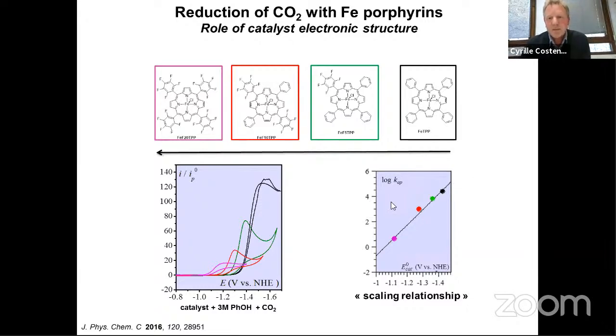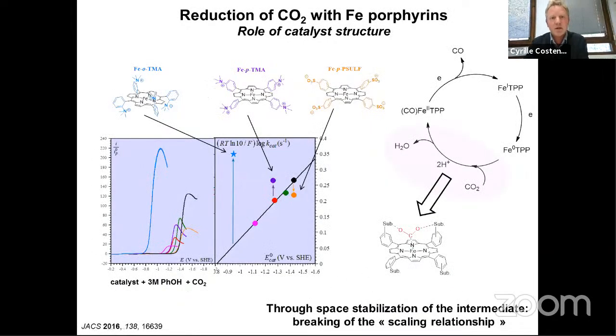Okay, so it seems that you are kind of stuck because what you would like is to get a high rate constant at positive potential, because as I said previously, the catalytic process is pinned at the standard potential of your molecular catalyst. Okay, so now the question is would it be possible to design a catalyst that will have a high rate constant but a positive standard potential? It seems from this correlation that if you use just electronic effect, it's not possible because of this scaling relationship. But we have shown that if you use through space effect, electrostatic through space effect, it's possible.